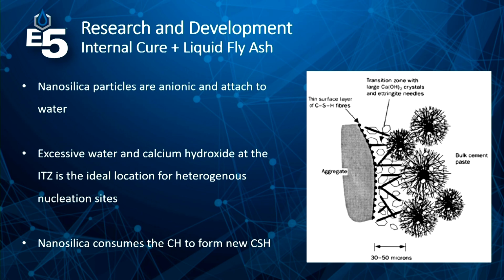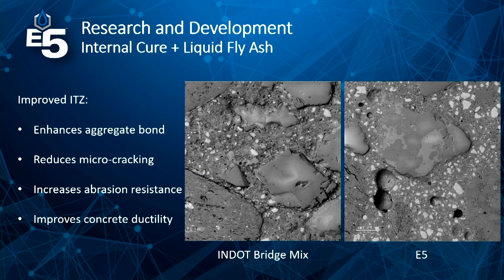Nanosilica particles are doubly negative charged, and they're anionic, and they're attracted to water, and they're much, much smaller than cement. So they weave their way into that area, and where that water and calcium hydroxide is becomes ideal locations for heterogeneous nucleation sites. Essentially, the nanosilica consumes the calcium hydroxide to form new calcium silicate hydrate.